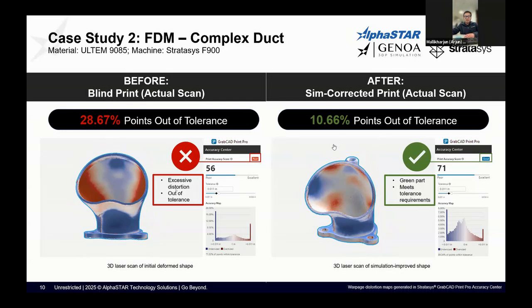Now, what we showed earlier, which is instead of going blind print and iterate physically printing these geometries, how about we simulate it? We bring the G-code in. In this case, it's the F900 machine. We bring the G-code in from the slicer. We bring it in with all the customizations for that specific machine. We simulate it so that at the end of the simulation, we predict what's going to happen if you print this specific geometry in that specific machine with the specific build characteristics that are intrinsic with that machine.